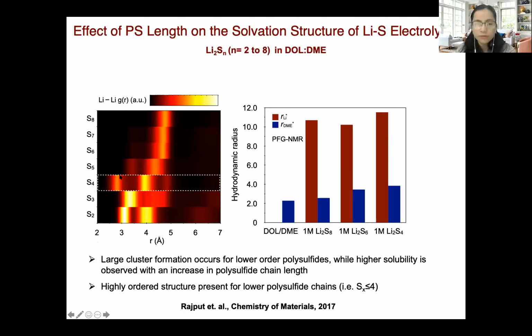In particular, we found that S4 has 2 sharp peaks at very short distance, and we found that we are forming this large polymeric structure of size almost 11 angstrom. And our experimental collaborators at Pacific Northwest National Lab used PFG NMR to measure the hydrodynamic radius of different lithium polysulfide species. And they found that indeed for Li2S4, we are forming very large clusters.